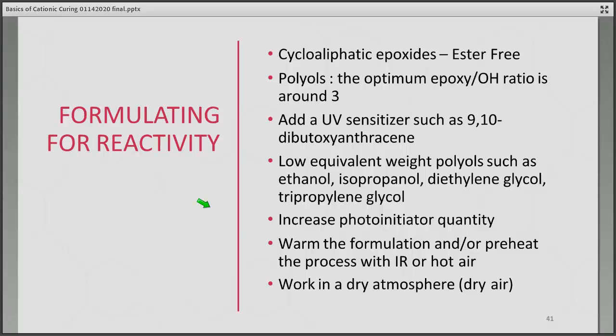Okay, let's start out with formulating for reactivity. If you need your reaction to cure at a greater speed, you can modify the cycloaliphatic epoxides. Ester-free cycloaliphatic epoxides tend to react faster. When you add polyols, the optimum epoxy to hydroxy ratio is around 3, so you tend to get the greatest cure speed at that level. You can add a UV sensitizer, such as 9,10-dibutoxyanthracene, one of the anthracene derivatives, to increase cure speed, and we saw that illustrated very well in the chart a few slides ago.